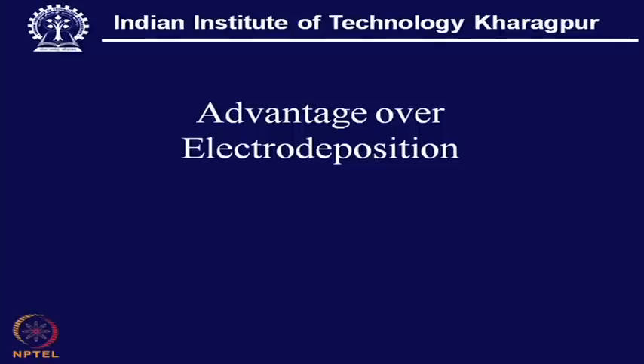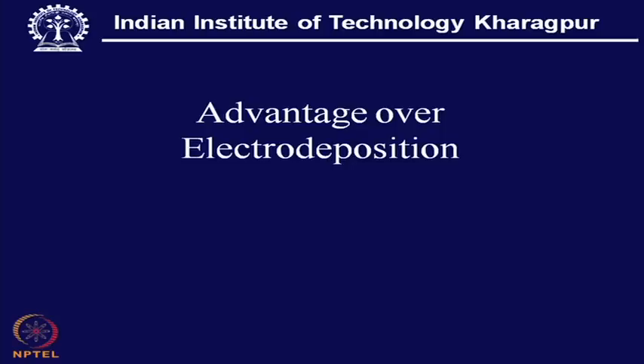And the advantage of this electroless over electro deposition is that in this case we do not need any electricity, you have a better uniformity of deposition, the substrate need not be conducting, and we can have a densification of the coating. So, these are a few advantages one can immediately extract from this electroless process. Only one limitation is that the surface of the substrate should be autocatalytic in nature.